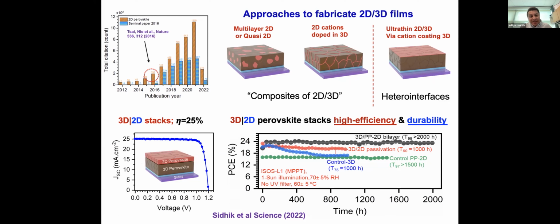But really the take home message is that you can get extremely high durability, which is shown in this black curve here. This is the device which we ran for about 2000 hours at about 60 degrees C, 70% humidity, and really did not undergo any degradation. And if you compare that to either the 3D device or the 3D/2D passivation layer that I showed you, or even the 2D control, you can see that you can synergistically combine the advantages of the 2D, get the stability of the 2D and get the efficiency from the 3D.